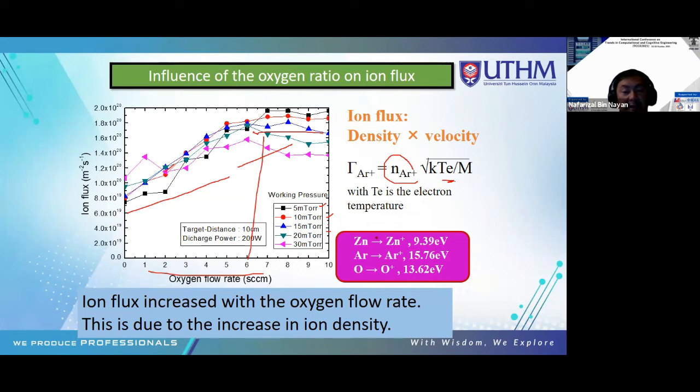And we can see, when we increase the pressure from 5 millitorr to 30 millitorr, that the ion flux decreases. Ion flux decreases when we increase the pressure.